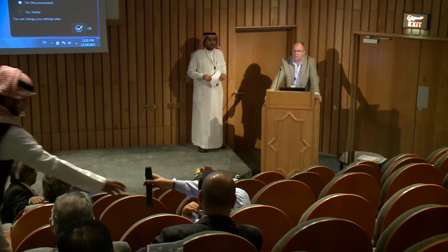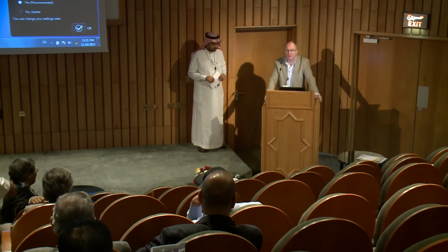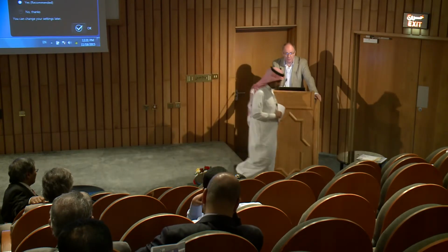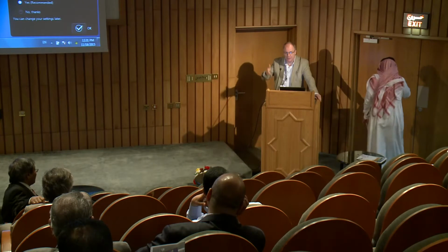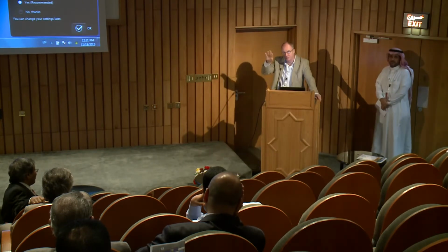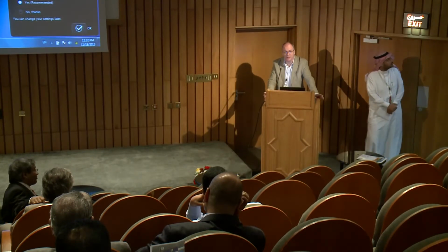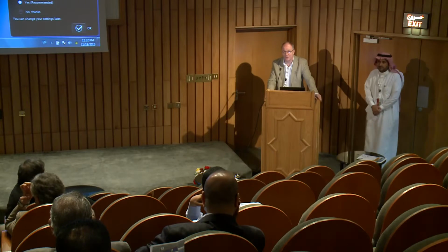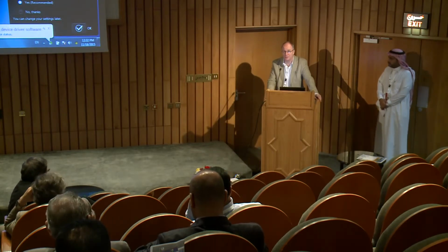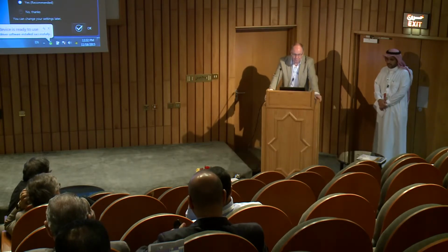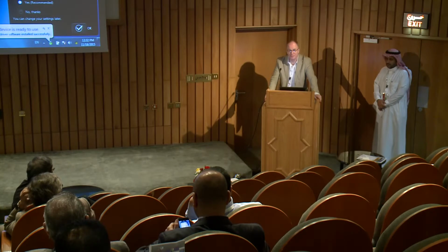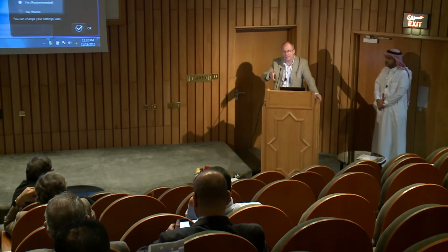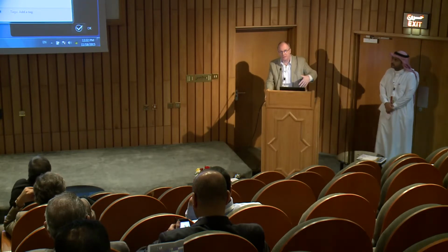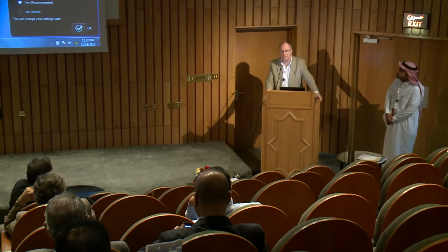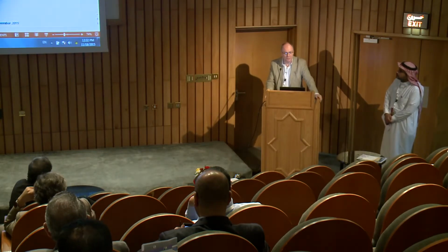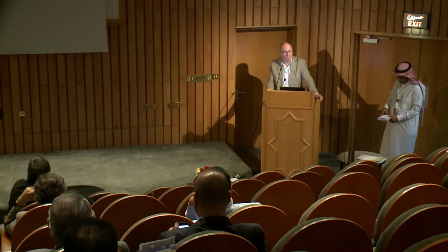Yes, I can, and maybe others, since it's a more general discussion, could fill in. To start with, I would think that with the extremely exciting improvement of efficiency, we must start to see some saturation in the efficiency. So the big question mark is, of course, stability for perovskite, and I would say that it still needs a lot more research. There are many reasons why it's not stable. We do see that halides can be mobile. We have an organic part which is freely rotating and can in principle evaporate. And then we have hole conductor interfaces and so on.